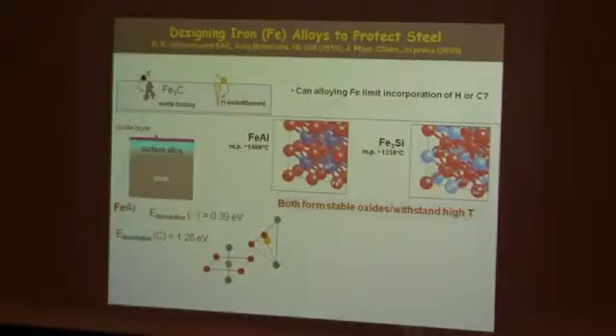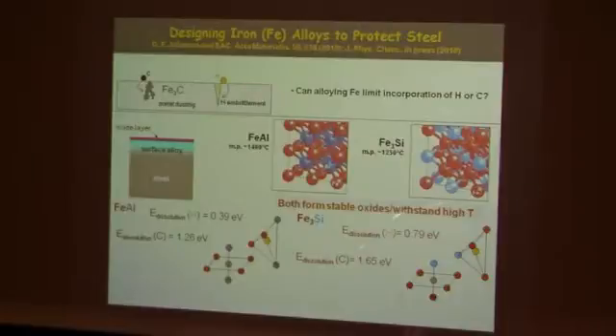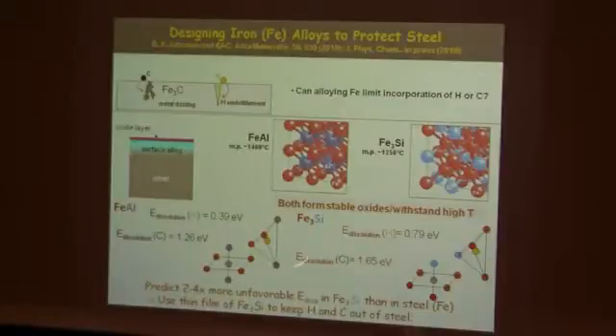But it turns out if you go to iron silicide, you find that the amount of energy that it takes to put hydrogen or carbon into iron silicide is much, much higher than for iron aluminide or for iron itself. And so it's actually 2 to 4 times more unfavorable to put carbon and hydrogen into iron silicide than into steel itself. And so one of the things we've suggested is that if you put a thin film of this iron silicide on steel, this would help protect the steel from hydrogen and carbon incorporation.